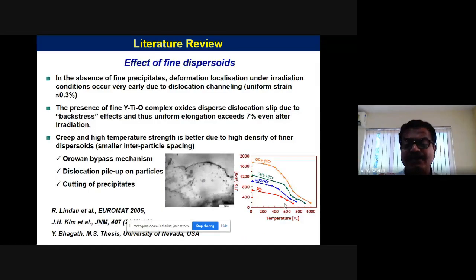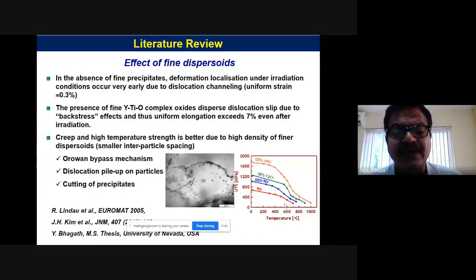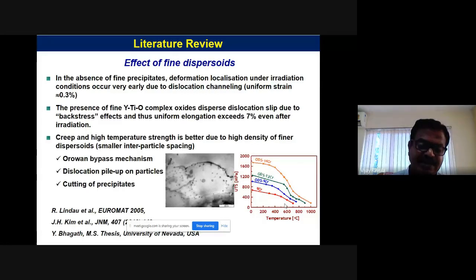And then finally, what is happening? What is the function of the oxide particles? See, when you are putting a stress, a lot of dislocations will be generated, and then these dislocations will pile up or move, and thereby the material will fracture if the density is very high. So when you have finely, uniformly distributed oxide particles, and this is a typical dislocation loop, they stop these dislocations from passing, and thereby you need to put some more energy or more force or stress to move those dislocations. So that's why the strength goes up.